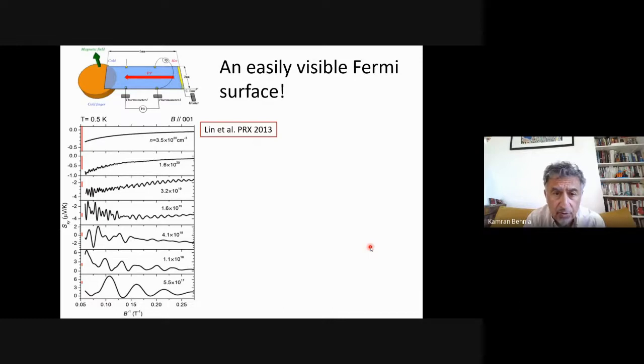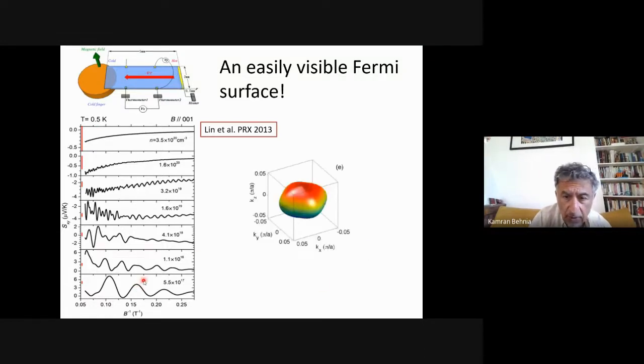So what we did in 2013 was to do some thermoelectric measurements. I'm not going to go into the details. We measured the Nernst effect, and we saw that you easily see quantum oscillations in the dilute limit. And what was interesting is that when you go to very low densities, 5.5 × 10^17 cm^-3, you have just a single frequency. You can see it here. And actually, the Fermi surface is very small.